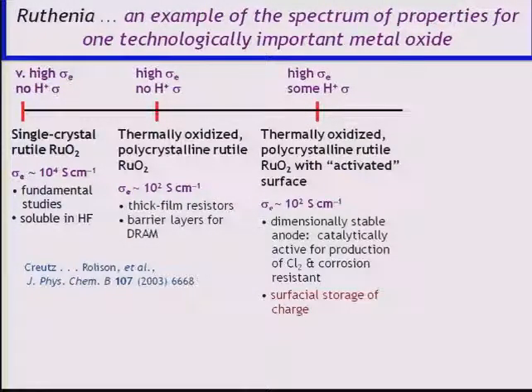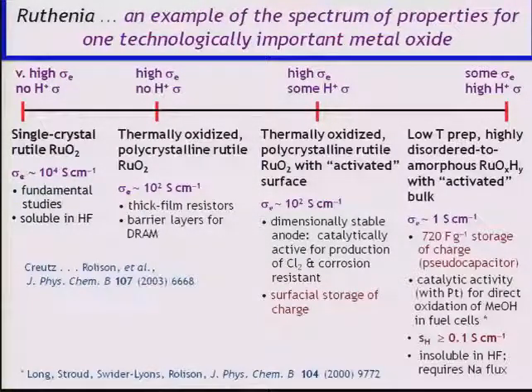In the 70s and 80s, it was recognized, well, even earlier, the dimensionally stable anode has a rather beaten up form of ruthenium dioxide as part of that anode that's oxidizing chloride to chlorine. Same conductivity and ability to store some charge at the surface. Conway and Trasatti in particular focused on that in the 80s. But the catalytic form of RuO2 that we found in direct methanol, when you just have pure hydrous ruthenium oxide, is the world's champion for charge storage, over 720 farads per gram. And that's per gram of ruthenium dioxide, which is heavy, unlike the 80, 90, 100 farads per gram you get with carbon, which is light.